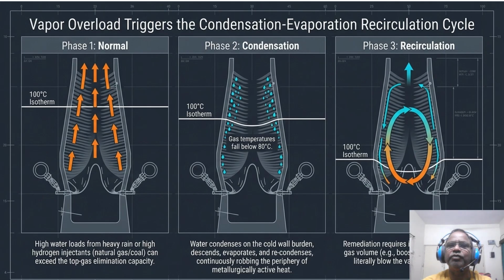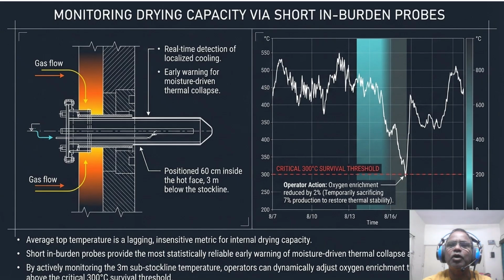In burden probe, average top gas is a lagging and insensitive metric. To get ahead of the thermal collapse, we look at the short in-burden probes. These are positioned 60 centimeters inside the hot face, roughly 3 meters below the stock line. Now look at the trend graph on the right. Notice the critical 300 survival threshold.